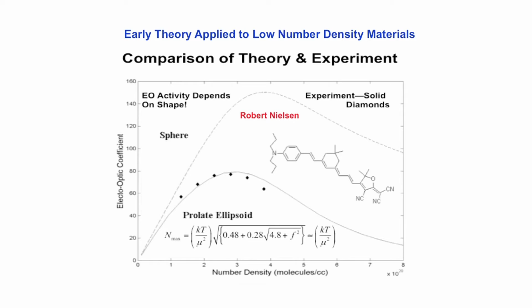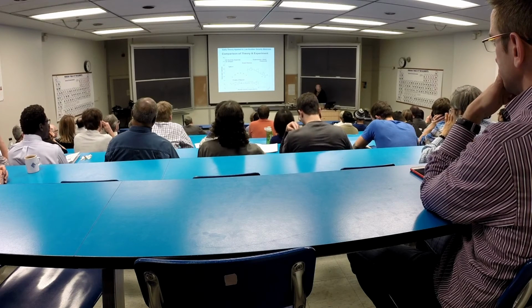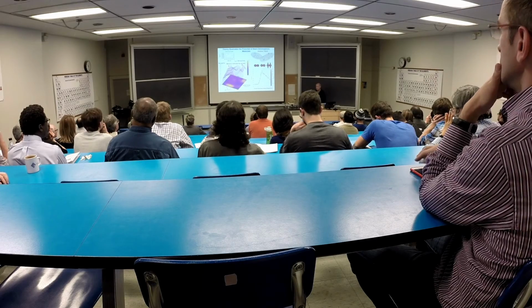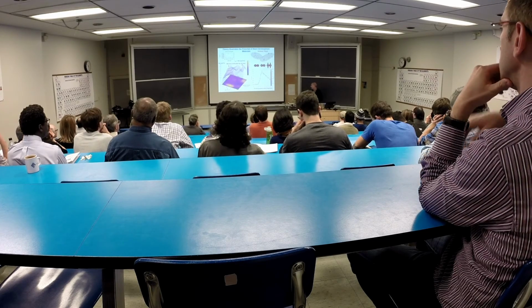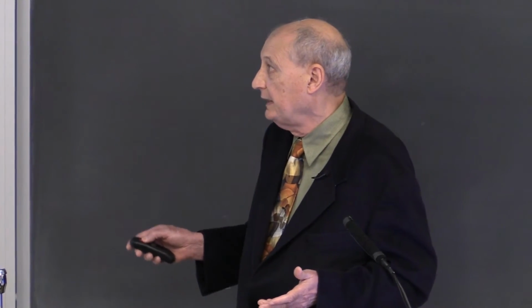But if you look at this, before I go to the next slide, you'd naturally assume this is just going to keep going down. You're going to get one maximum here. Up here, you're going to be centrosymmetric organization. In fact, if you take this chromophore and just grow a crystal in the absence of a poling field, it's going to crystallize in a centrosymmetric configuration. But you'd be wrong, and as shown